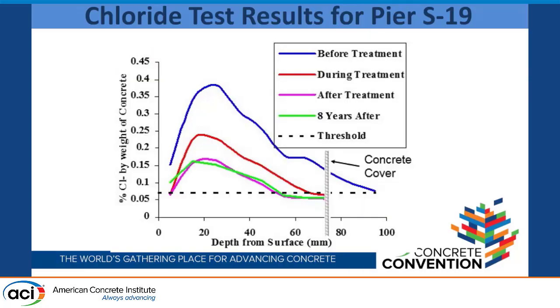This is a graph showing the results from that pilot project. The blue line shows the initial chloride profile, average of, I can't remember, 4 or 6 different cores that they took within the area that was being done. From the surface of the concrete back over here, back to the depth of the reinforcing steel back here. And you can see that the chlorides back at the steel were above the threshold. And then through the treatment, the chlorides reduced. And then there's a line on there, the green one, which was some cores that they took 8 years after the treatment, because one of the questions was, would the chlorides redistribute or come back into the concrete more than before? Didn't really move around much.